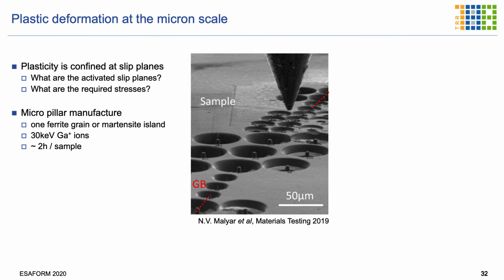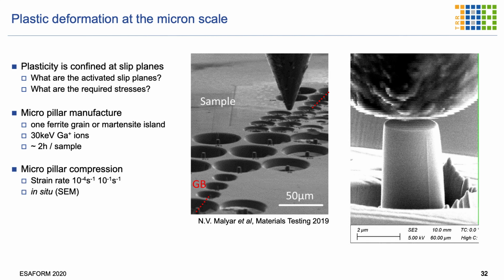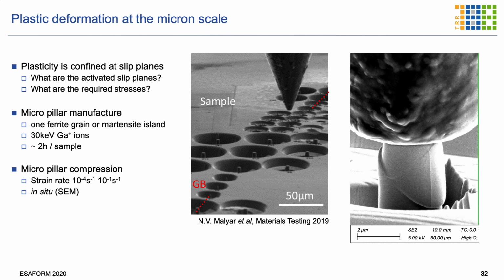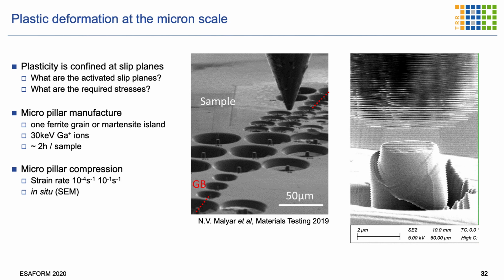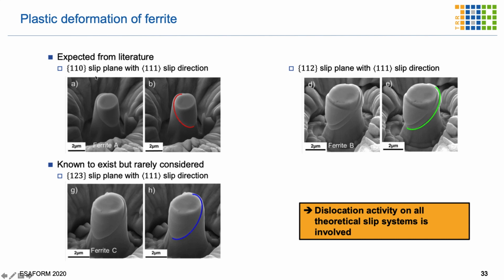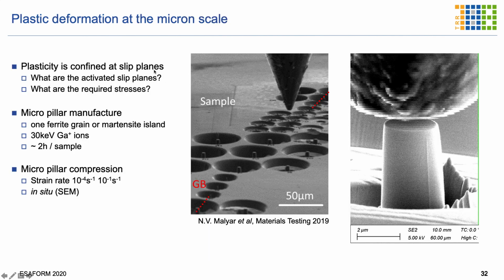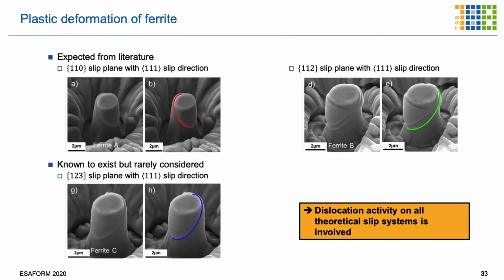Another important thing is to determine the plastic properties of our material. And for that purpose, we used again some micro pillar compression tests and found the slip lines. An interesting result is, if you look to literature, you expect the 110 slip plane with the 111 slip direction as the typical slip system, but what we found is dislocation activity on all theoretical slip systems is involved in the plastic deformation of this material. So one very important result.